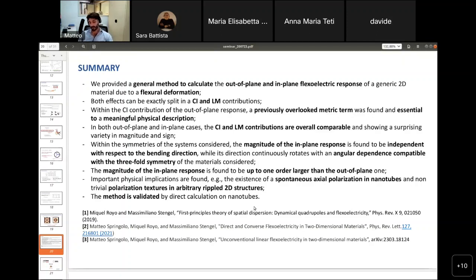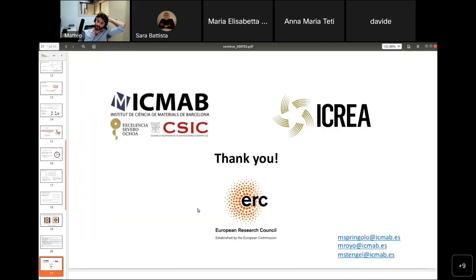Finally, we found that the in-plane response turns out to be much larger than the out-of-plane one, and in many cases up to almost one order larger. Finally, we presented the physical implications of such an effect in describing the general polarization field in a two-dimensional structure. Also, we benchmarked our method by means of calculations in a set of nanotubes. Thank you.